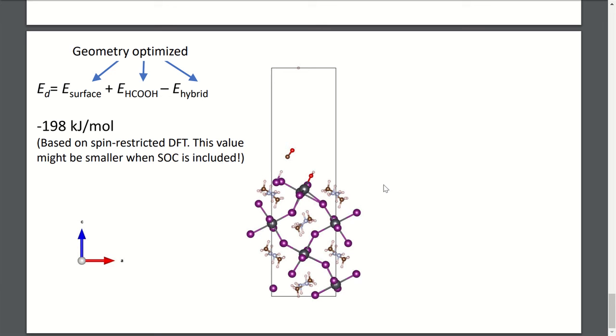In your previous work, there was a guess of the presence of cavities, a special shape of defect. And right now it is not needed. In the previous work, the binding energies were diverging very much from experiment until we guessed that there is a cavity-shaped defect. That is pretty close to the TDS, I guess. Well, not really a quantitative match, but I guess that's close. Molecular desorption, yes, medium molecular, and then you have a high temperature peak. Those two. So the first two numbers would maybe match the experiments.